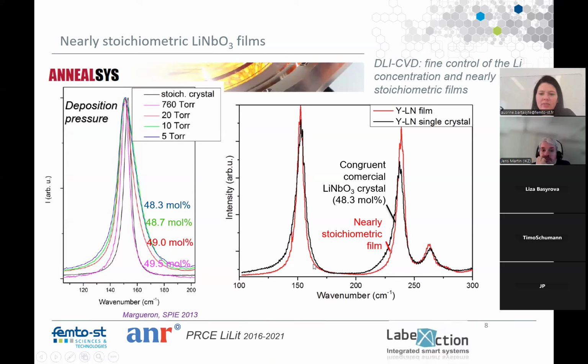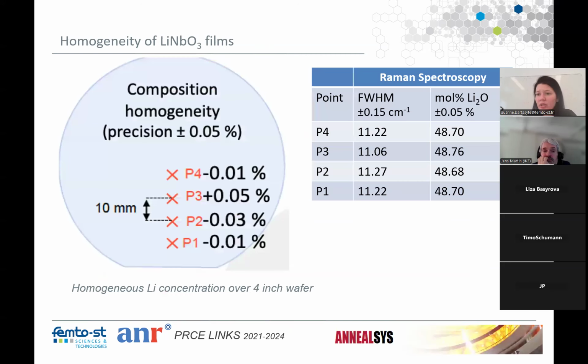As you can see here in the Raman spectrum of a film, in red, the modes are thinner than the modes of a single crystal of the same orientation, which indicates that the film contains fewer defects than congruent crystals. We also measured the composition homogeneity across the wafer; we were one of the rare groups to measure lithium composition inside films. And additionally, almost nobody showed homogeneity over large surfaces.